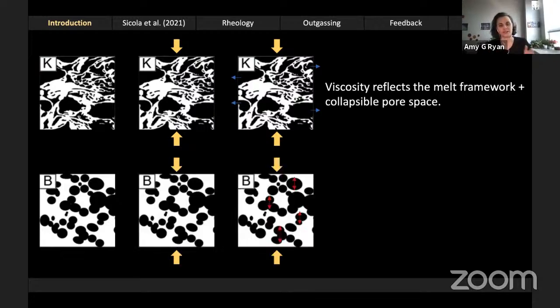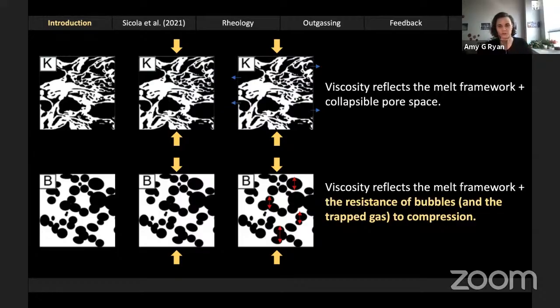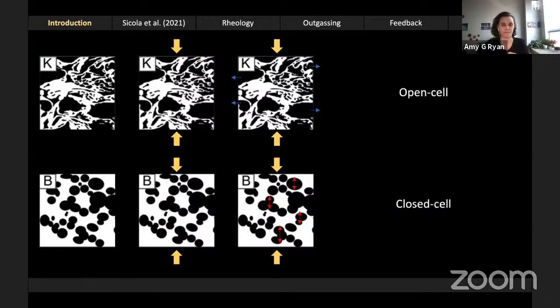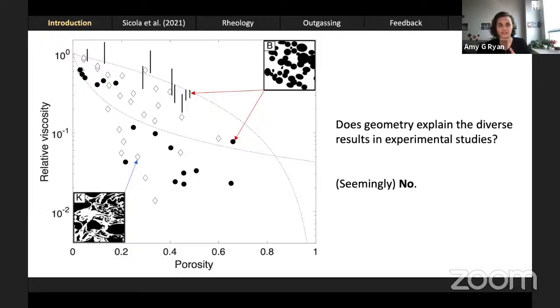In contrast, if I try to compress the material on the bottom, B, you can imagine as I'm compressing, the pore fluid in those bubbles doesn't really have the same opportunity to escape from the system because of the low connectivity. So any viscosity I calculate when measuring something like this will reflect the melt framework again, of course, but will also tell me something about the resistance of the bubbles and the gases trapped therein to compression. If I borrow some terminology from material science, we can call the material on the top open cell and the material on the bottom closed cell. So as a first pass, can we understand the diversity of the experimental results that we have so far by looking solely at pore geometry.